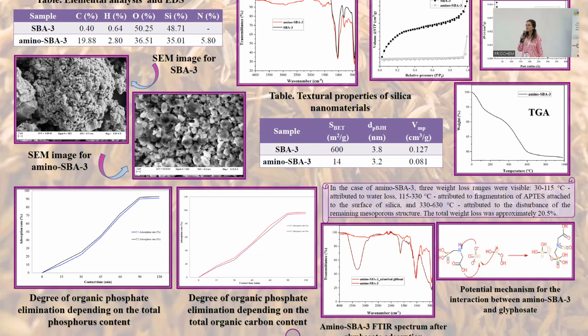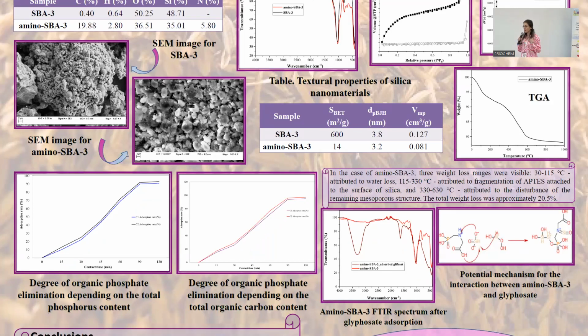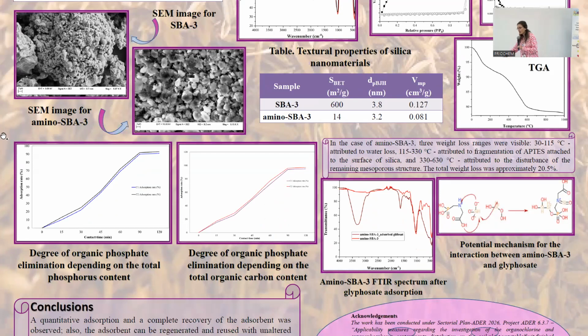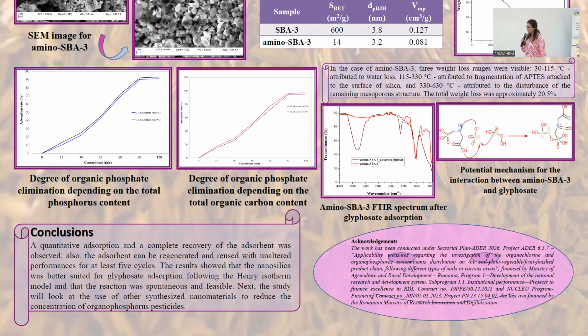And we saw that pseudo second order kinetics and Langmuir isotherms were the better model, which confirmed that the adsorption rate depends on adsorption capacity and not on the concentration of the adsorbate. We also performed some FTIR spectra, and we saw that glyphosate functional groups were present within the pores of our aminosilica materials. In conclusion, a quantitative adsorption and a complete recovery of the adsorbent was observed. The adsorbent can be regenerated and used for at least 5 cycles.